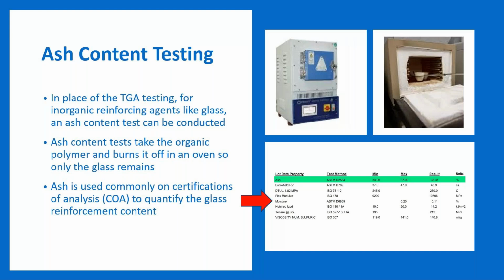Essentially, for ash content testing, you take your organic polymer, so ABS, and it's filled with glass, and it burns off the ABS in the oven, and it only leaves the glass remaining. And so they're able to measure that and give you an idea of how much glass is in the material. So when we say it's a 30 glass filled nylon, 40 glass filled nylon, whatever it may be, generally then what you should be seeing on a cert, so certification of analysis, so this is all the tests done on that particular lot of material that was made, ash content should be on there for your filled grades.